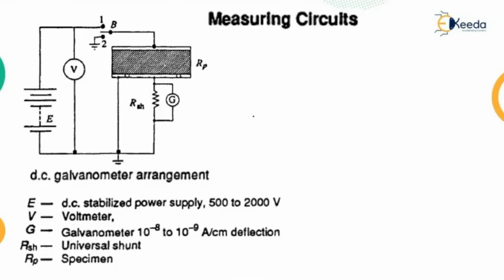Now let us understand the measuring circuit. Here you can see the test specimen which is placed here. So let us understand this circuit. Here we have a battery source, that is a DC stabilized power supply, that varies from 500 to 2000 volts. So it means 0.5 kilovolt to 2 kilovolt. Here there is a voltmeter, a measuring device. There is a galvanometer of 10 to the power minus 8 to 10 to the power minus 9 ampere per centimeter deflection. Then RSH is the shunt resistance, and the resistivity of the material to be tested is of this specimen. Here we have a switch connecting point 1 and point 2. Point 2 is the grounded terminal, so we can toggle between point 1 and point 2.